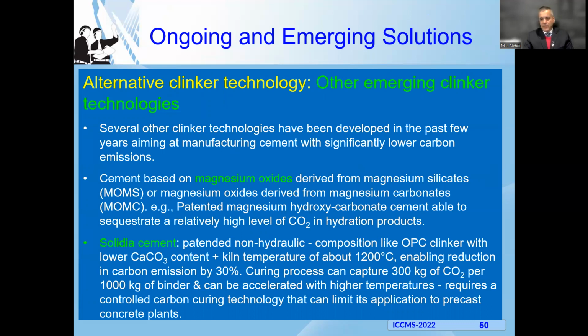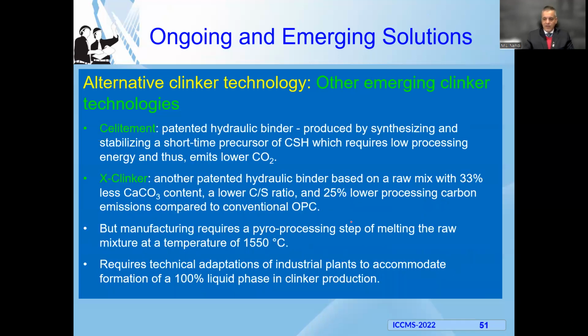So essentially, it uses less calcium carbonate in its formulation. Its kiln temperature is lower. Instead of say 1450 Celsius, you would need somewhere around maybe 1200, which is significant. It enables reductions maybe of carbon emissions by 1/3. In addition to this, the curing would be using CO2, and then maybe for 1,000 kilograms of binder, you could capture maybe 300 kilograms of CO2, which is very significant.